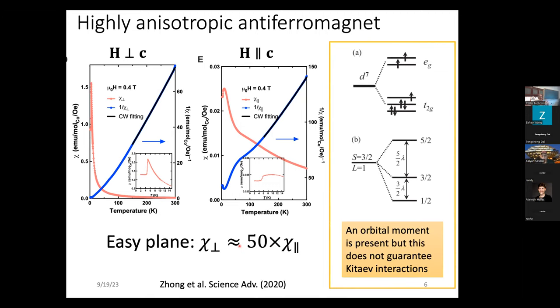Now, this strong anisotropy immediately alerts us to the contribution of the orbital magnetism in this material. And this is what we should expect and we'll always see in these 3d7 cobalt compounds. The argument for that could be constructed as indicated here. This is using Hund's rule. We can develop the total spin angular momentum and the total orbital angular momentum, and both of those are actually finite. They then combine by spin orbit coupling.